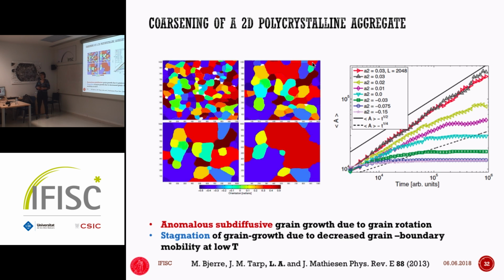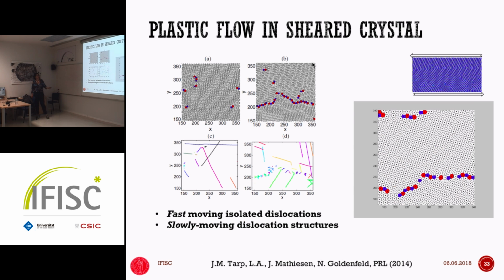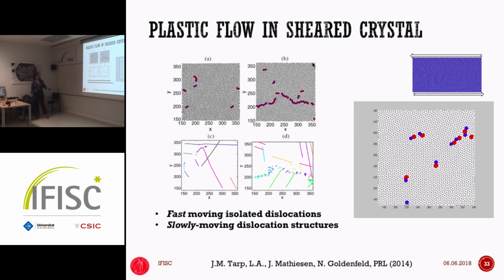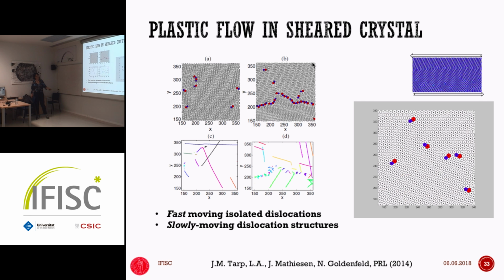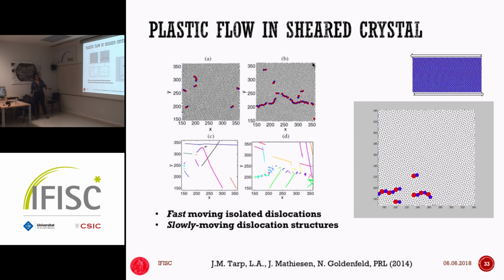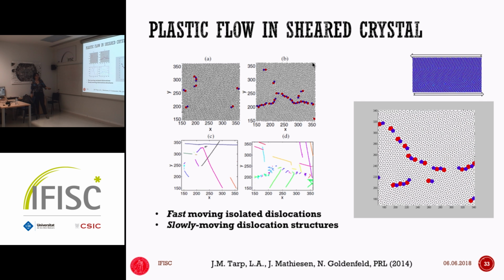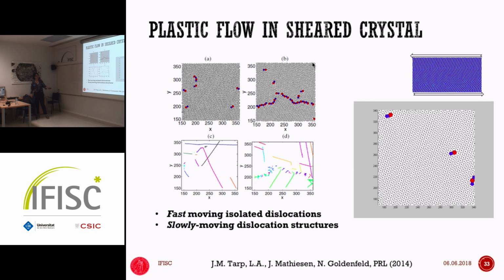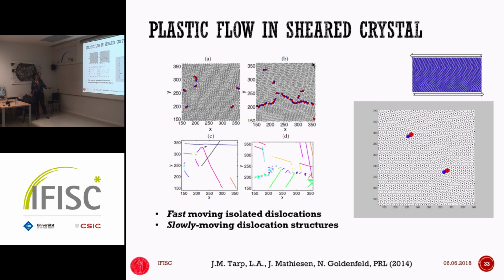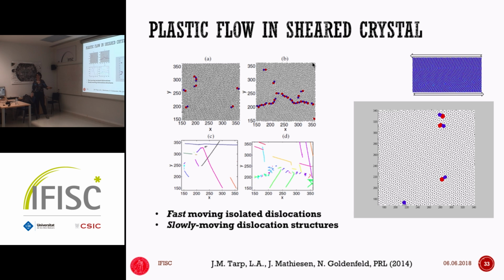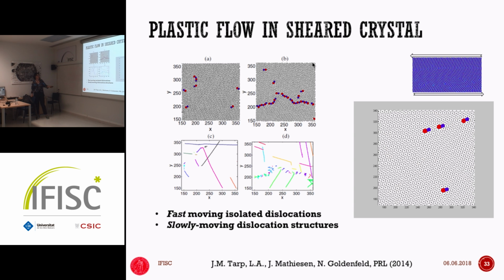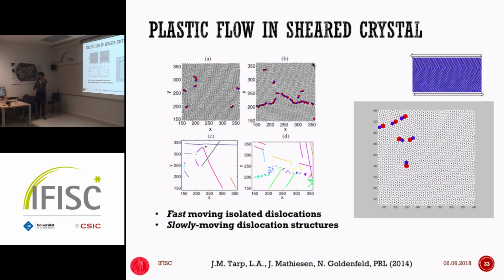So in processes like epitaxial growth or other processes where you want to control the microstructure, depending on the temperature that you are working on, it might be very difficult to get rid of it. And this is quite nicely captured in this thing. And you can also study the defect dynamics. You can see that in a single crystal they can move around, and sometimes they can form these transient domain walls like grain boundaries. So when they are trapped together in a grain boundary, they move much less. They kind of jiggle around the mean velocity of the grain, whereas when they are isolated, they can just move with the Rayleigh speed.